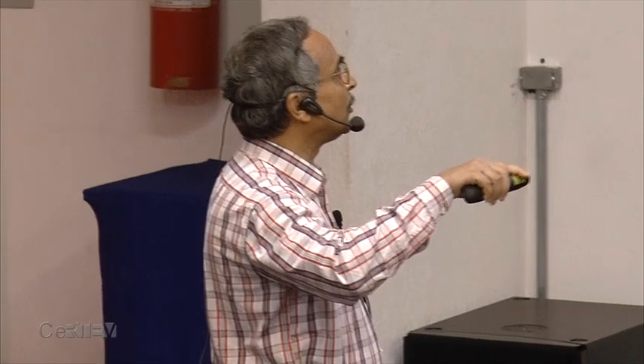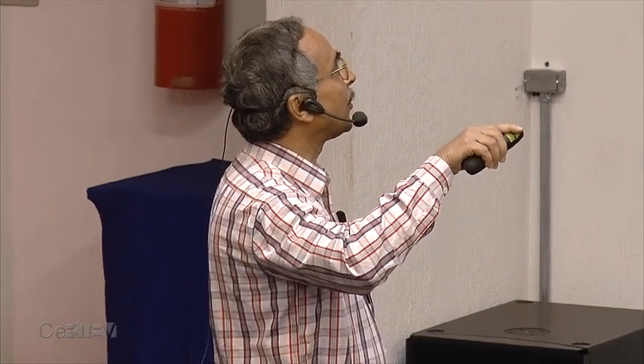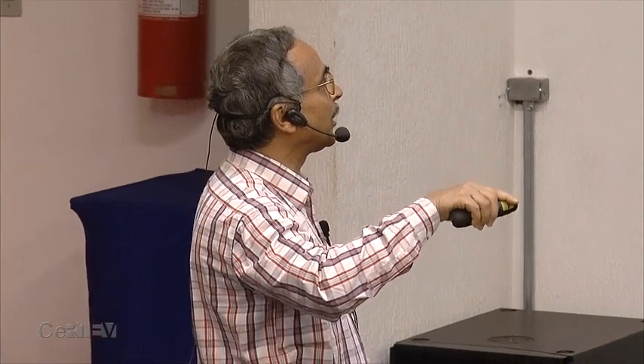then you can see that it is behaving in a similar way as the conductivity. Here the conductivity was increasing with the increase of the lithium ion content. And also the long time behavior is behaving the same way. So we can at least correlate the conductivity and the characteristic length in such glasses, because the ion dynamics in these glasses is not a fixed parameter, it is dependent on the structure of the glasses.